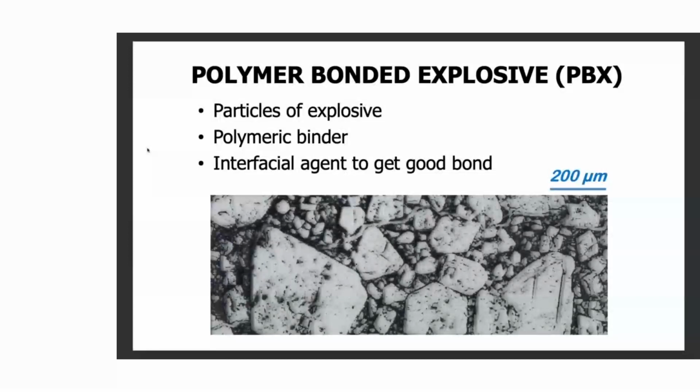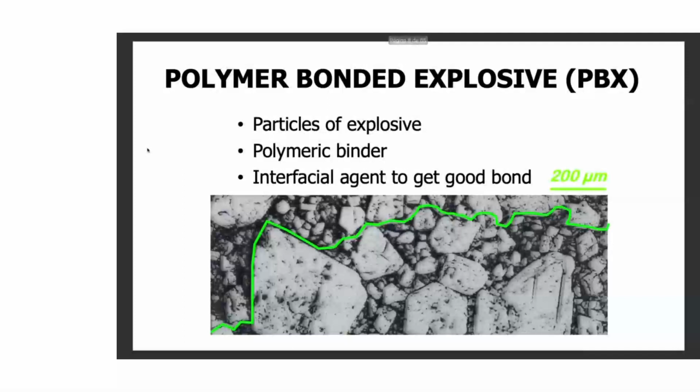When you have a crack forming in this kind of system at low temperatures, you generally find that the cracks and the damage follow along the polymer part, so you're basically tearing the polymer open. So that's a key point in the system.